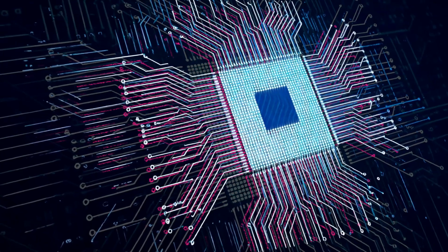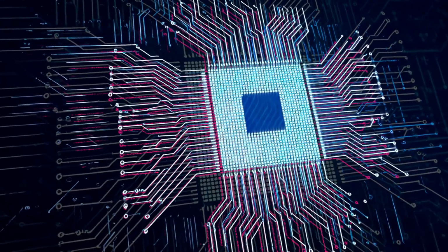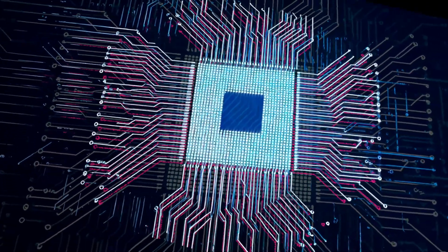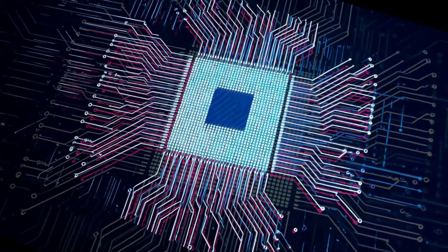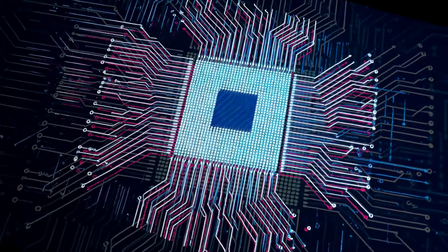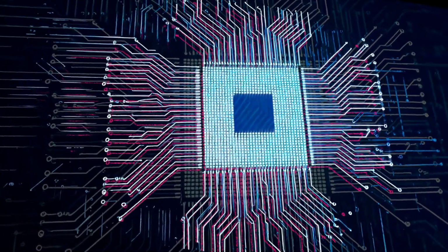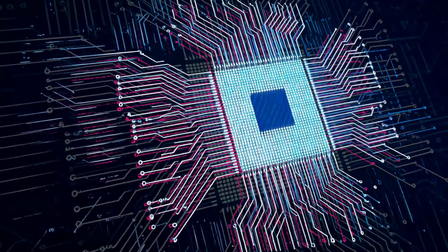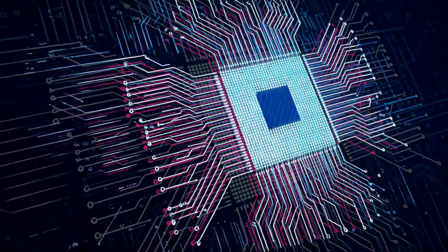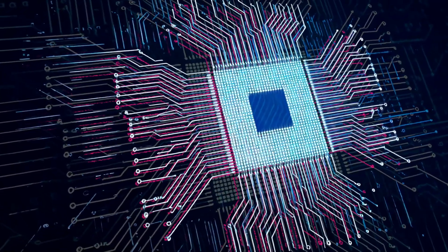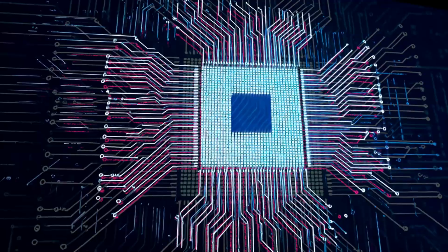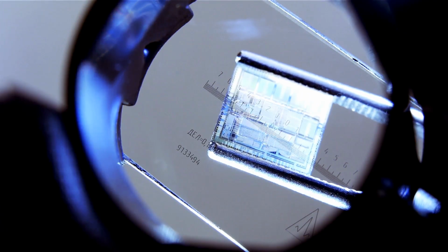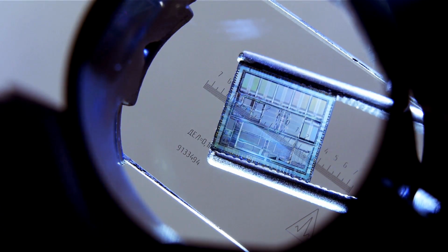A multi-junction concentrator cell operates under 1,000 times normal sunlight intensity. That means 100 watts of optical power focused onto a square centimeter of semiconductor. The cell converts roughly 40% of that light into electricity. The other 60% becomes heat, inside the cell, almost instantly. 60 watts of heat inside 1 square centimeter of gallium arsenide.